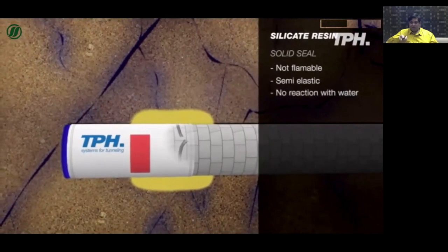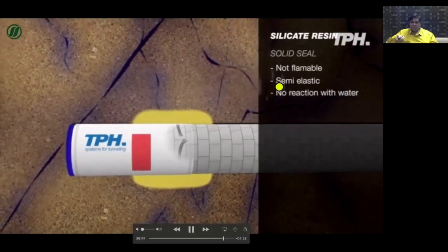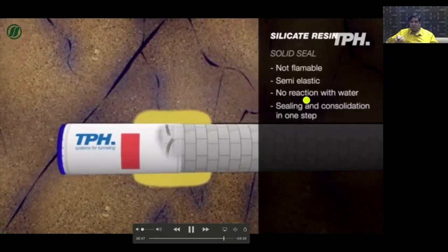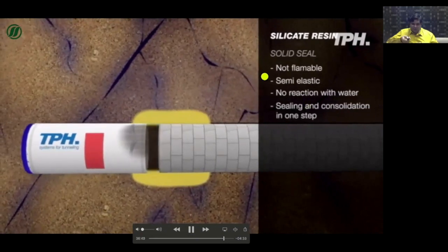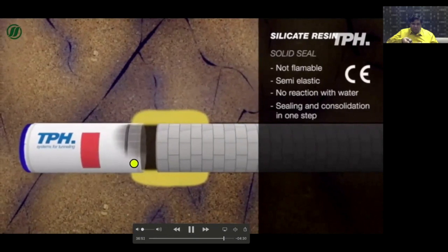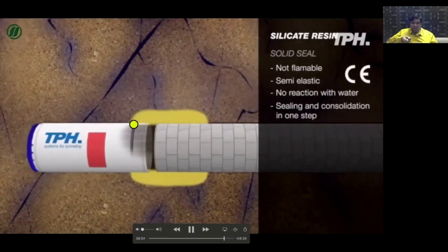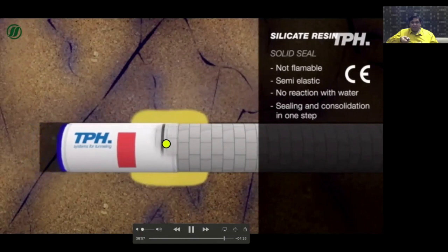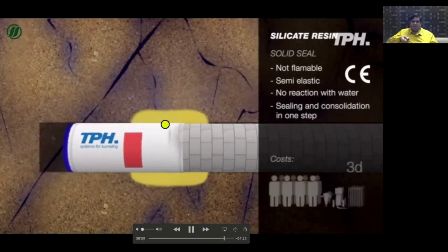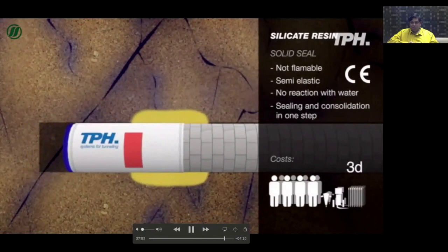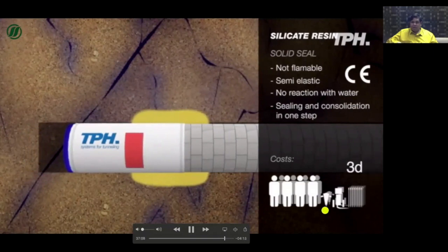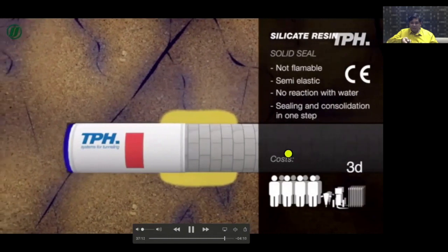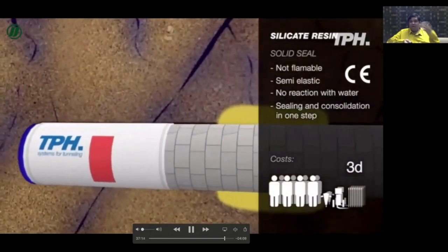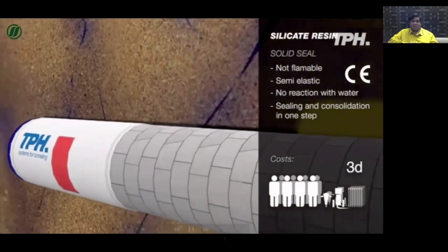A few of the advantages were that there was no problem of flammability, it was semi-elastic in nature, and there's no problem with the water. Once this area was consolidated, they could easily move the TBM a little bit and replace the tail seal, and then the tunneling could easily continue. In terms of costs, it was a certain manpower and maybe 3 days. In 3 days they could resolve this entire problem. If the TBM had continued and there was a cave-in, that would of course be a much more expensive disaster.